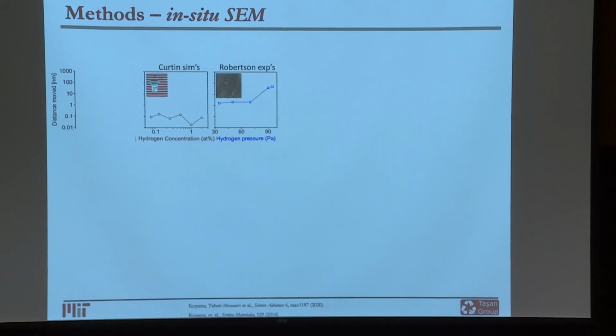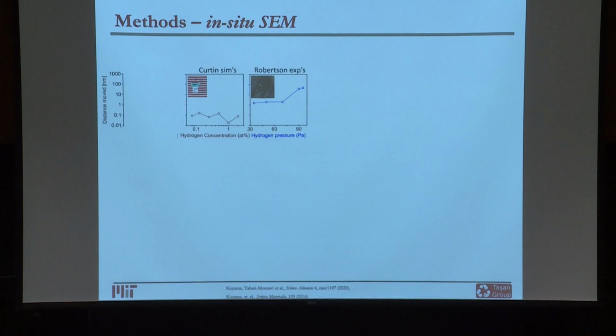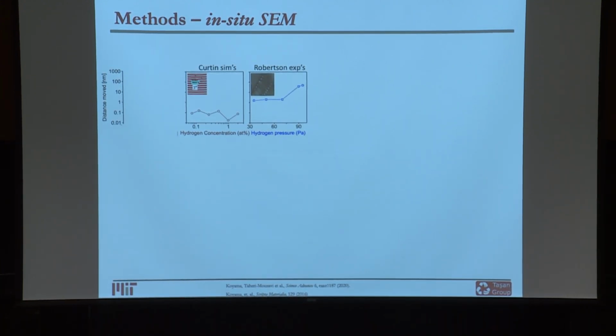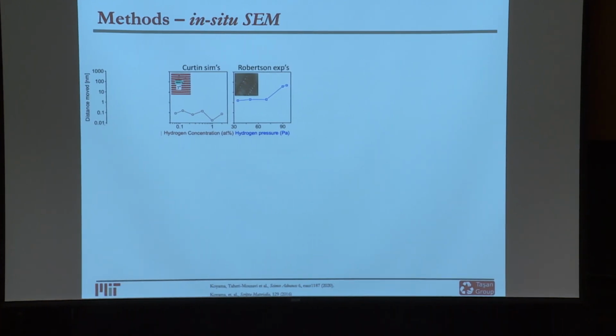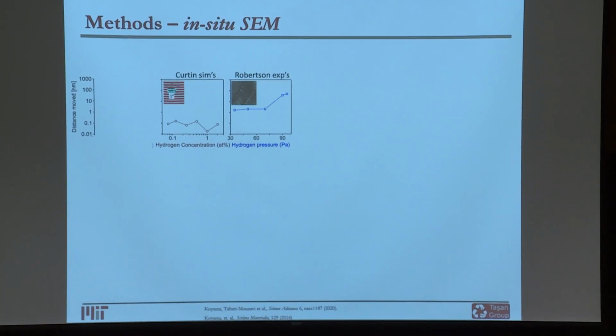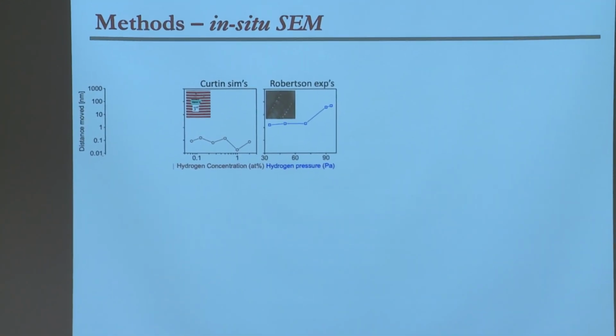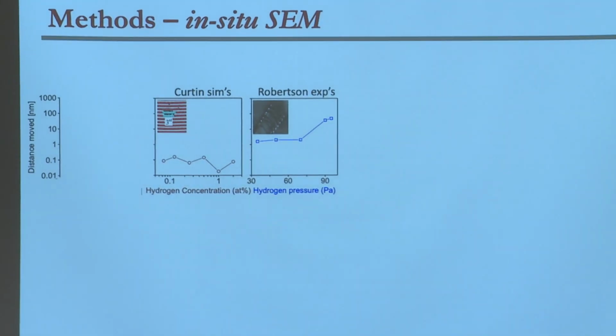One of the other dilemmas in the literature was about hydrogen's effect on dislocations. It was already shown by the beautiful experiments by a transmission electron microscopy group that hydrogen can come to dislocations and basically change their spacing. But these experiments were not confirmed by atomistic simulations that basically say that hydrogen would decorate a dislocation, like a more conventional interstitial effect, essentially creating an atmosphere, a Cottrell atmosphere around the dislocation, limiting its motion. Rather than causing it to move, it would limit its motion. So we were looking at this and thinking, maybe our in situ techniques can help us.